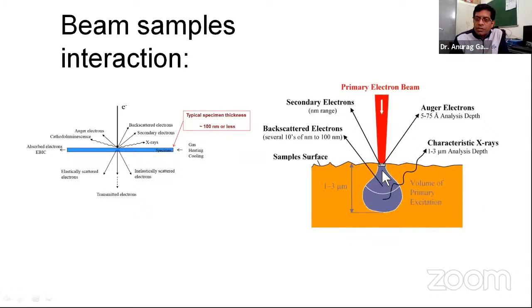So that is the primary electron beam, and that is the upper surface of your sample, and the depth is being shown. So from just the surface come the Auger electrons, and Auger electrons come from 5 to 75 angstrom. This is the thickness. So they are totally from the top of the surface. Then the secondary electrons come from a depth of up to 10 nanometer. So they are just coming from up to a depth of 10 nanometer in the sample, and the backscattered electrons are maximum up to 100 nanometer.